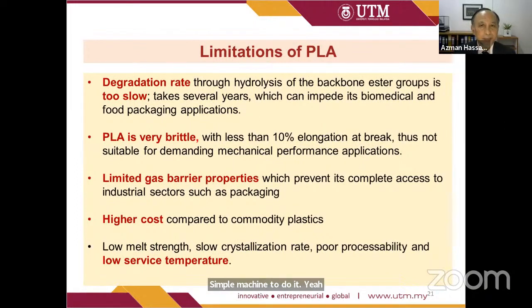PLA is very brittle, with less than 10% elongation at break. It has limited gas barrier properties, which prevents its complete access to industrial sectors such as packaging. It has higher costs compared to commodity plastics such as polyethylene or polypropylene. It has low melt strength, low crystallization rate, so the percentage of crystallinity is rather low, poor processability, and low service temperature compared to other polymers.